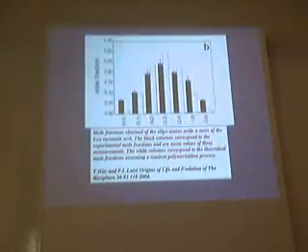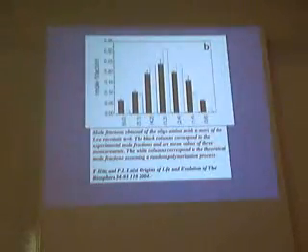Now, Luisi studied several systems, but if you go now to leucine, we could get up to hexamers, but he uses the amino acid itself as the initiator. Because the amino acid itself is a zwitterion, the concentration of the pure amino acid NH2 is very low. We have done some NMR studies on these systems, and we can see that the polymerization competes very seriously with hydrolysis.